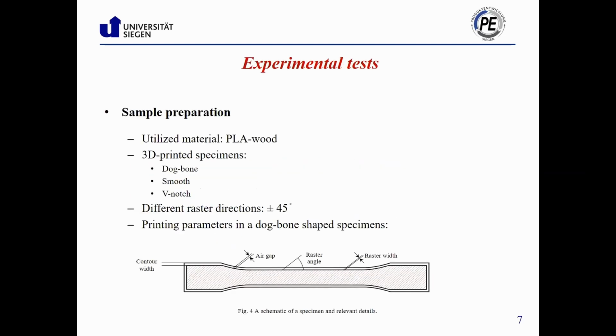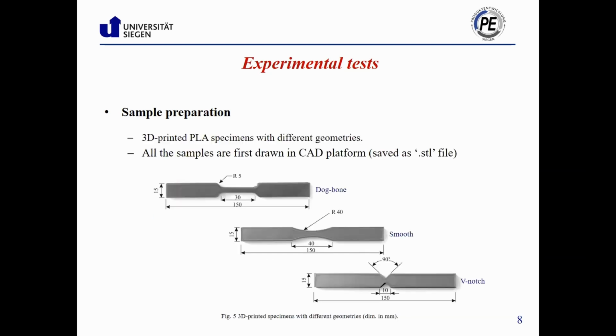In preparation of the specimen, here we designed the specimen with 3 geometries we call dog bone, smooth, and V-notch. All specimens were printed with the raster direction plus minus 45 degrees, and by definition, raster direction is the printing direction relative to the loading direction. In the figure, you can see the details of the printing in a dog bone shaped specimen. In this slide, you can see 3D printed specimens and their details.